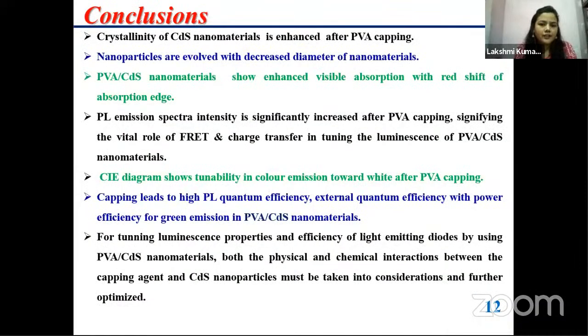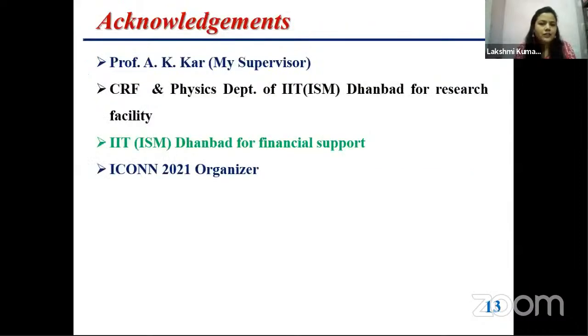And after that, here I conclude. After capping, crystallinity increases and the nanoparticle diameter decreases, and visible absorption enhances, and PL spectra show there are some chances of energy and charge transfer after capping, and also for tuning luminescence property and efficiency of light emitting diodes by using this nanomaterial. For PVA and CdS, both physical and chemical interaction between the capping agent and CdS nanoparticles must be taken into consideration in further optimization.